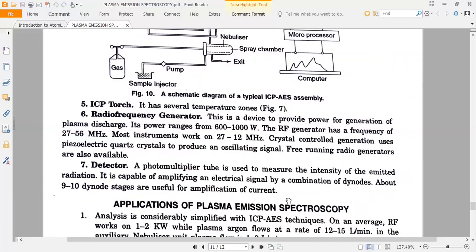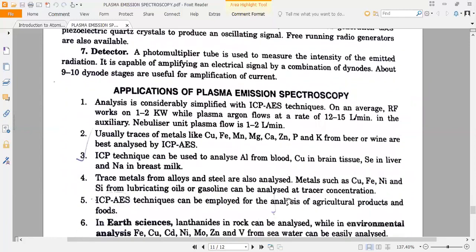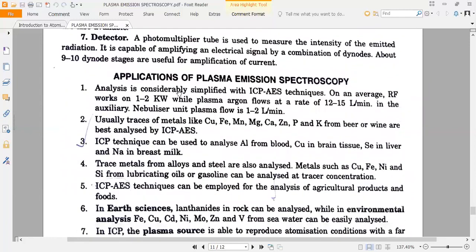And finally, the applications of plasma emission spectroscopy. Analysis is considerably simplified by the ICP-AES technique. On an average, RF works on 1 to 2 kilowatt power, while plasma argon flows at the rate of 12 to 15 liters per minute in the auxiliary. Nebulizer unit plasma flow is 1 to 2 liters per minute.